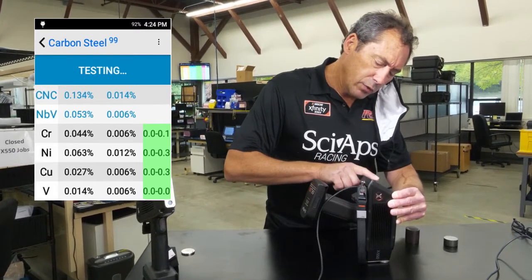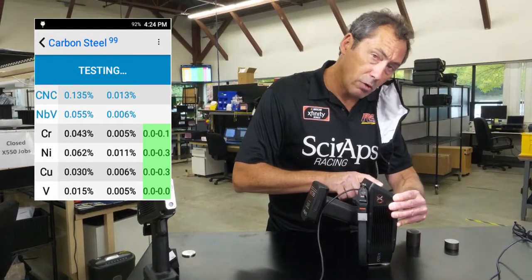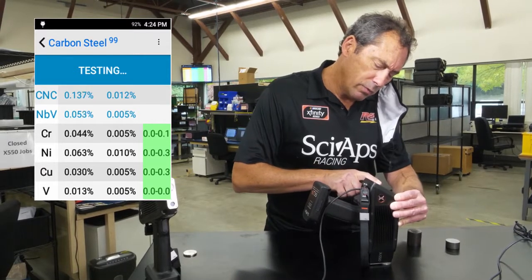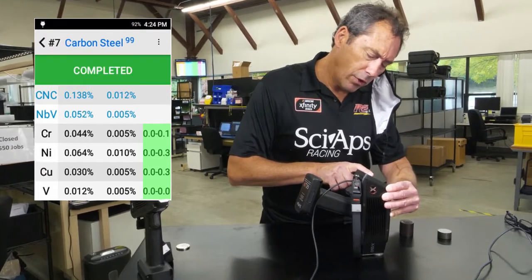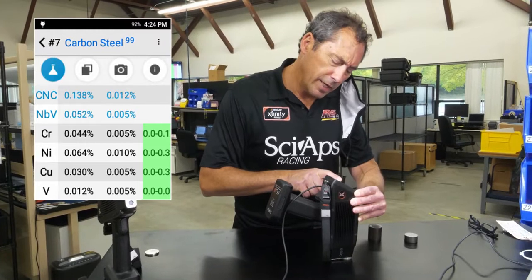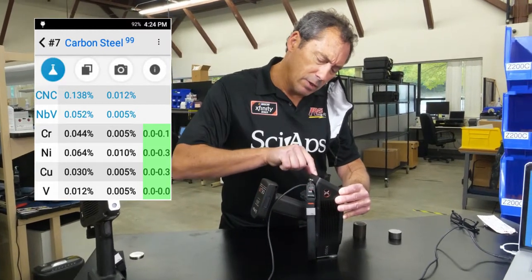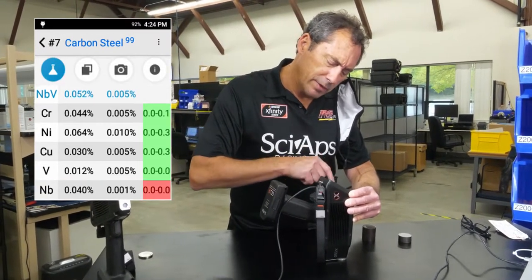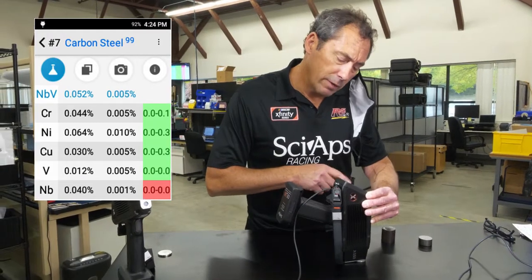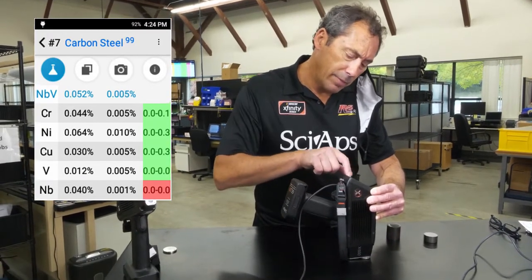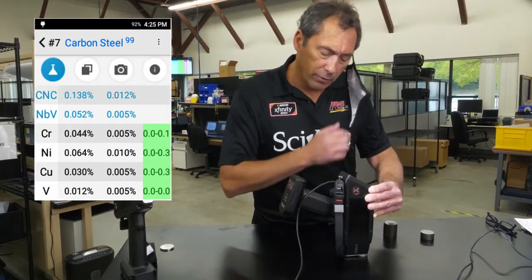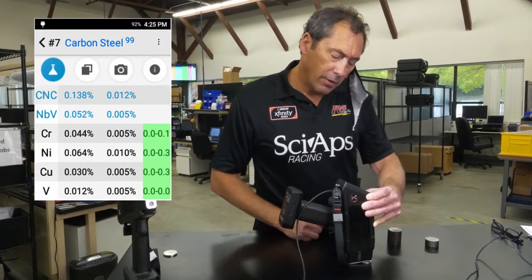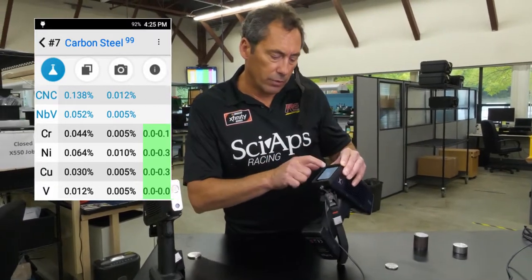And so this would pass on chrome, nickel, copper. But you see it will fail the 0.03 threshold on niobium plus vanadium. Vanadium's nice and low, down around 0.012, but niobium in the sample's high, it's about 0.04. So that would fail on the niobium, vanadium, but it would pass on the copper, chrome, nickel, whatever your requirement is. And that is how you do residuals.